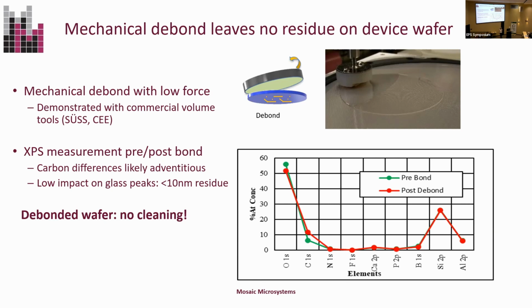One of the nice things is that our bond doesn't leave residue on the wafer. And we've checked this with XPS. What I'm showing here is a variety of elements that we were looking for. We checked the glass prior to bond, and then we debonded and checked it again. And there's a very slight variation in the carbon. That's within the noise of what we would see for a plasma cleaned piece of glass and one that has sat in the room for an hour. So it's basically about the amount of adventitious carbon that you expect on a piece of glass in the room. So there's basically no cleanup. And anybody who's paranoid about it can throw it in a 10-second oxygen plasma and then be guaranteed that's pristine glass again.